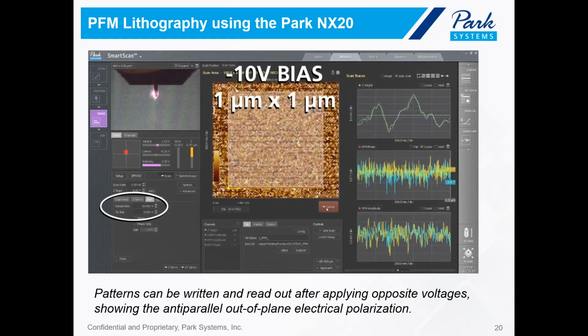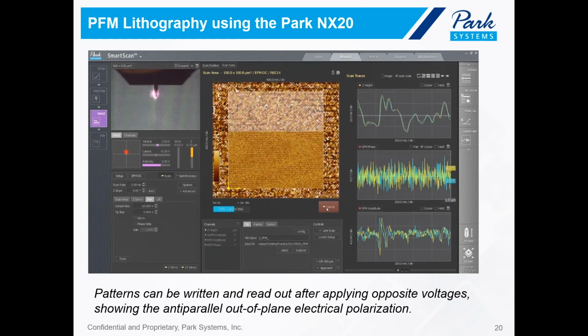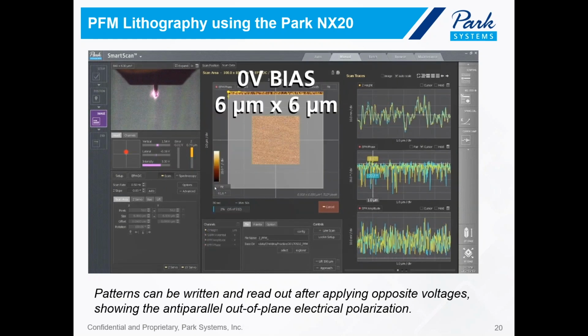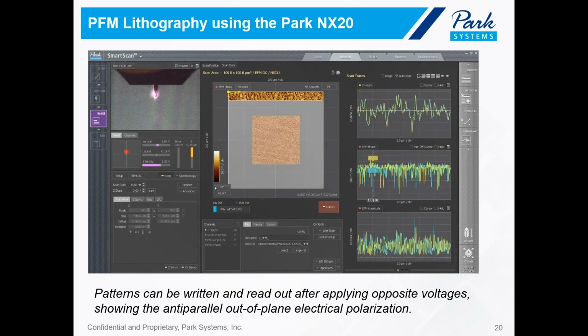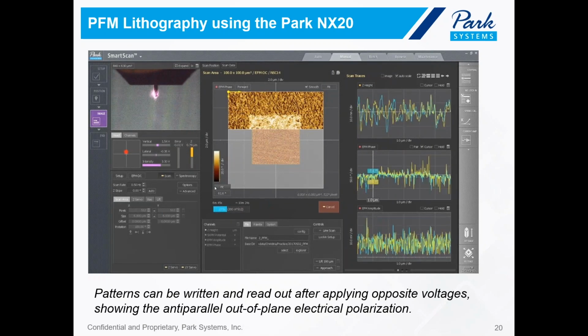And next, we zoom in. In the center of the 3 by 3 micron, we scan a smaller region with negative 10 volt tip bias. This is a 1 micron by 1 micron scan. So finally, to read out, 0 volt DC bias applied to the tip, we scan a 6 by 6 micron region. And here is the result.